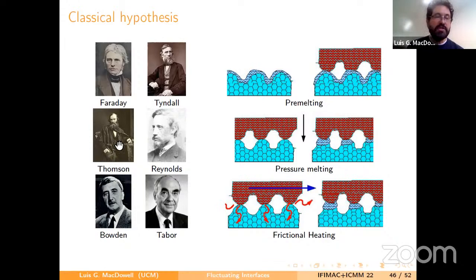But James Thomson, who was the brother of Lord Kelvin, argued that this could not be, and that instead, because you have asperities, when you put the slider on top of ice, the pressure is so high that it melts. And he suggested this because he was the one who discovered that ice melts under pressure. Okay, so that was his hypothesis. And then eventually Bowden argued that this could not be the case, that the pressures attained in these asperities could not be equal to the melting pressure. And so what he suggested is that when you have sliding, the sliding is heating the ice, and by heating it, you are melting it.